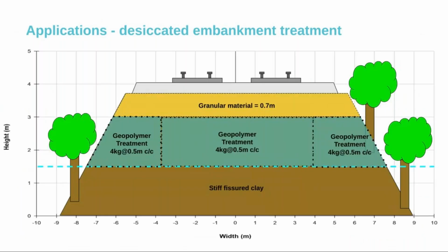What we can do with this technology is inject the geopolymer into that fissured clay layer. We inject very frequently, so a lot of injections, but small quantities of geopolymer. That way we can fill all these fissures within the clay to seal them off and stop the roots of the big trees nearby from sucking the moisture out.